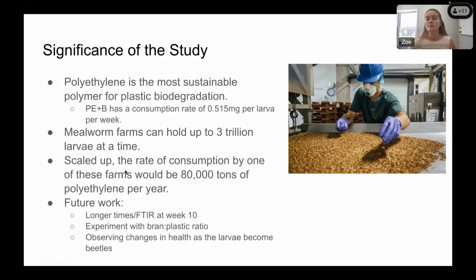So in terms of significance, polyethylene is the most sustainable polymer for this plastic degradation. And if we scale up this rate of 0.515 milligrams per larva per week, one mealworm farm can hold up to 3 trillion larvae. And so scaled up, this is 80,000 tons of polyethylene degraded per year if fed to one of these farms. And so this has the potential to make a huge dent on the